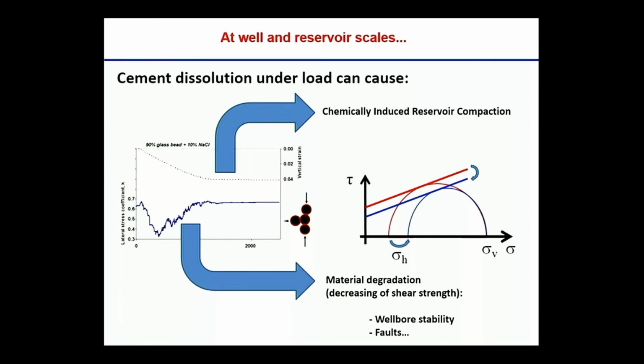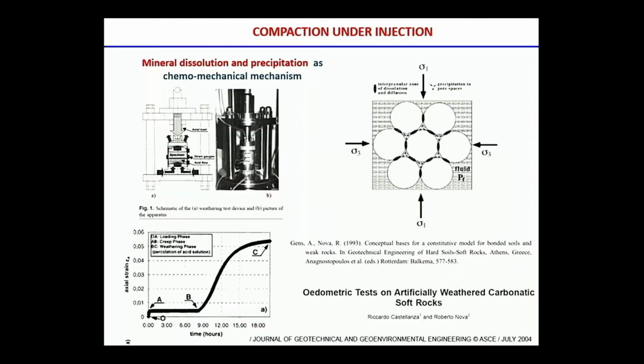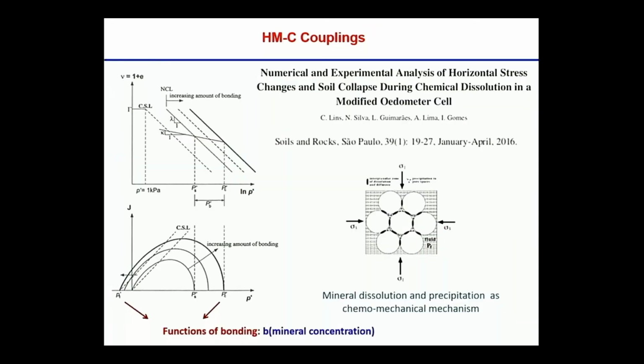Well, some consequences, for instance, at the well and reservoir scales: cement dissolution under load can cause chemically induced reservoir compaction, and also material degradation, and that will affect wellbore stability, reactivation of faults, and so on. There are other tests in the literature and models based on critical state models that are more sophisticated, that can introduce other effects, such as not only the loss of strength, but also the decreasing of pre-consolidation stress when we have material degradation.